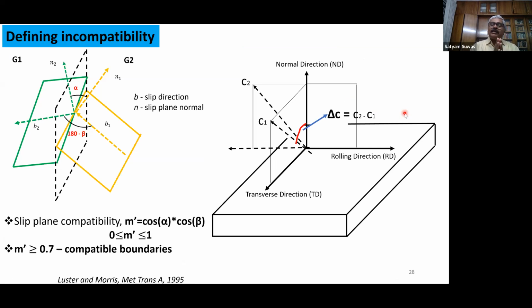Then, going back to the Stroh model for soft and hard grains, and also the misorientation between two grains, we tried to examine the incompatibility between the grains, and we used the Luster and Morris criteria for defining whether a particular slip plane is incompatible with the slip plane in the other grain. This was measured by a parameter called m prime, as given in the Luster and Morris paper. These are the two angles, cos alpha and cos beta. Alpha is this angle and beta is 180 degrees minus this angle. So we measured the slip plane compatibility here, and the criterion is that if this m prime is more than or equal to 0.7, then the boundaries are compatible.